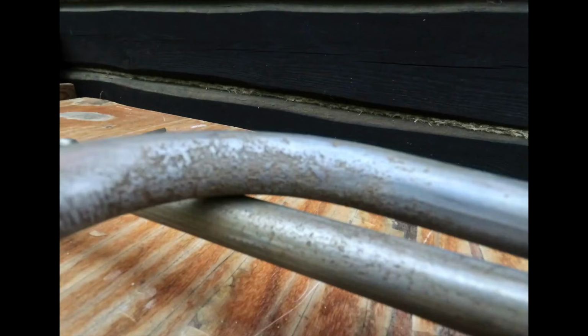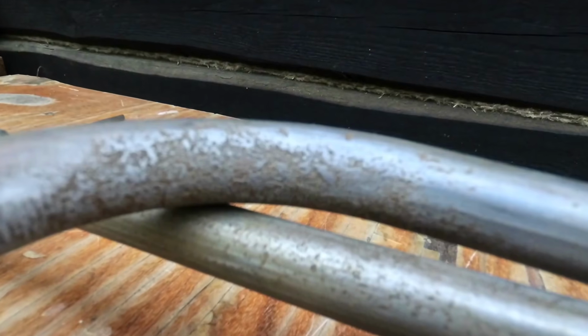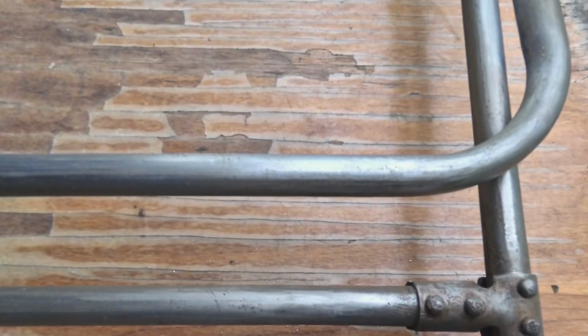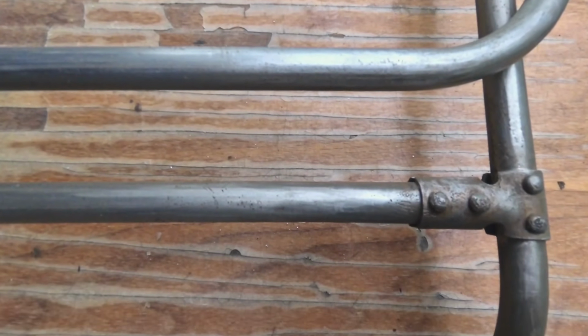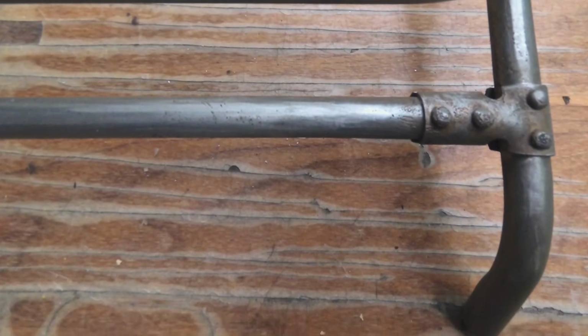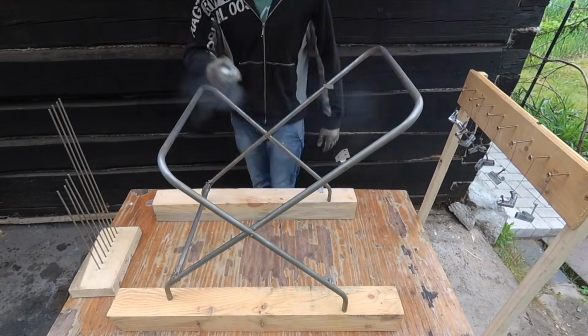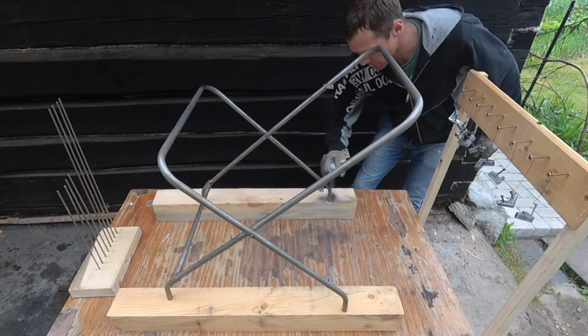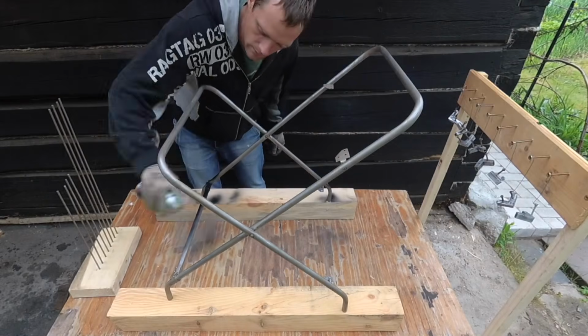And I finally got the chrome off. But, as you can see, the salt solution had damaged the part quite badly, so table salt isn't suitable for electroplating. Before painting, be sure to prime and coat the part with 3 coats of matte black paint.